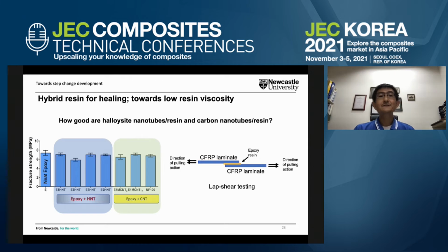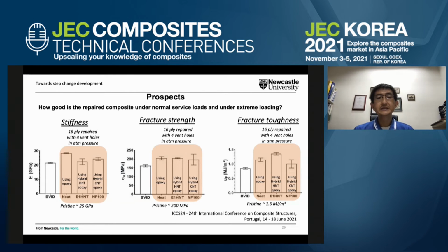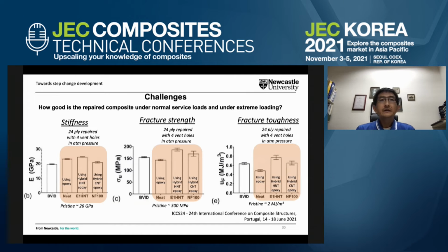So with all these findings, we then move on to see how we can do the repair of damaged composite, and how good is the mechanical property of the repaired composite under normal service loads and under extreme loading, of course, is what we are interested in. We did this for 2 types of laminate, the 16 and the 24 ply. And we find to our delight that the repair efficiency with regard to stiffness, fracture strength, and fracture toughness is very good for 16 ply, reaching as close to pristine condition. However, with increasing thickness of the laminate, like the 24 ply, we find that the repair efficiency is not too good.